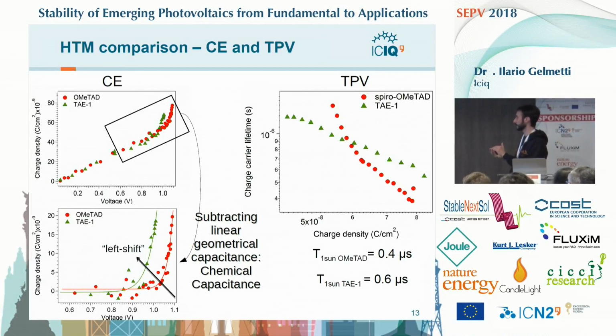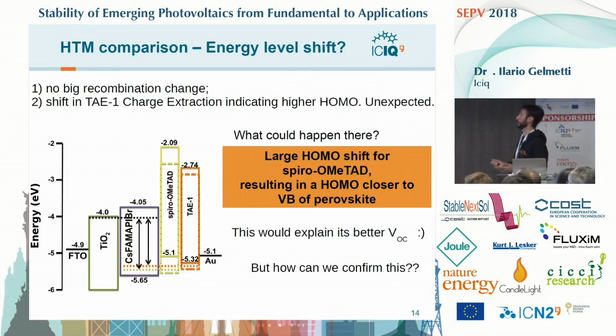So this shift indicated that the spiro-OMeTAD HOMO level was closer to the valence band maximum of the perovskite, while from the HOMO level calculated from cyclic voltammetry we expected the opposite. So we expected the TAE1 HOMO level to be deeper, so these exponential parts should start later, at higher voltages. So we saw no recombination change. We saw this shift in the wrong direction.